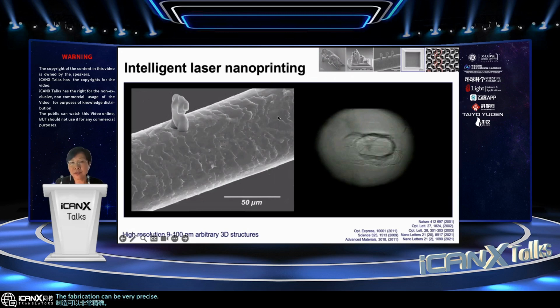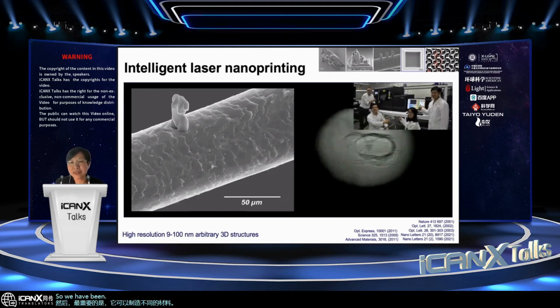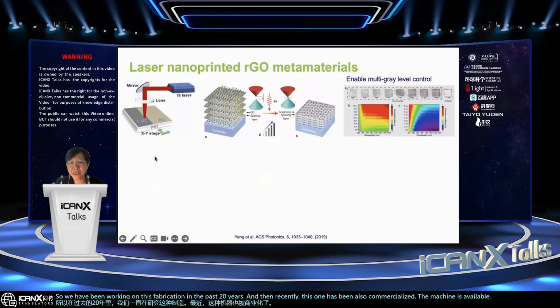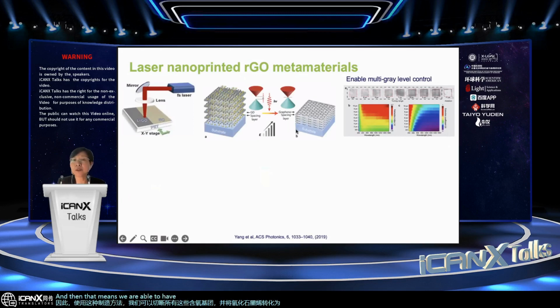The highest resolution achieved if you use 2-beam can reach 9 nanometers, and most importantly, it can fabricate different materials. We have been working on this fabrication for the past 20 years, and recently this has also been commercialized. The machine is available. Using this fabrication method, we can chop off all these oxygen-containing groups and convert graphene oxide into graphene. That means we are able to have quite good quality using a simple and low-cost method. During the laser reduction, you will see that with different laser power, the color of the graphene oxide becomes increasingly dark. That means you're closer to graphene.